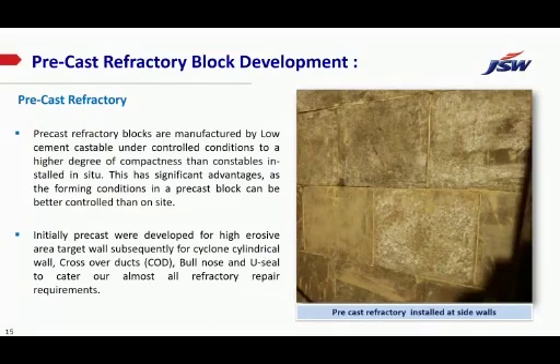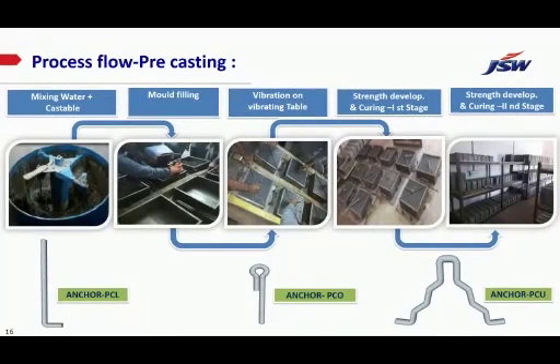The precast refractory is nothing but prefabricated refractory blocks that are fabricated in completely controlled conditions in the workshop, where adequate water, adequate mixing, and all quality parameters are maintained. There we fabricate the precast. The fabrication process is on the screen. For that, we mix the refractory material with water in the mixer, then pour this material into the molds, place these molds on the vibrating table, and provide vibration for about 2 minutes. After that, leave the molds for curing for 24 hours.